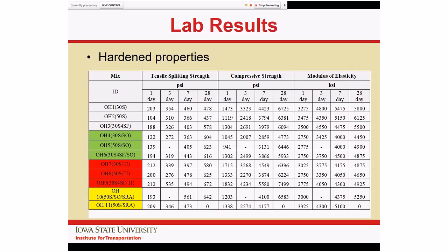Again, a table full of the hardened properties. Again, the flexural strengths are all pretty similar. Compressive strengths were all well above 6,000 psi, or pretty close to 6,000 psi at 28 days. The one that I did want to flag here was that the modulus of elasticity was notably lower for the systems containing the lightweight fine aggregate here on the middle right-hand side of the chart.